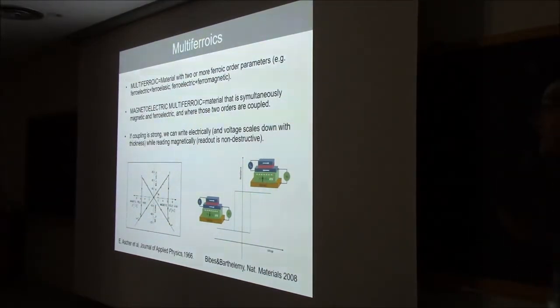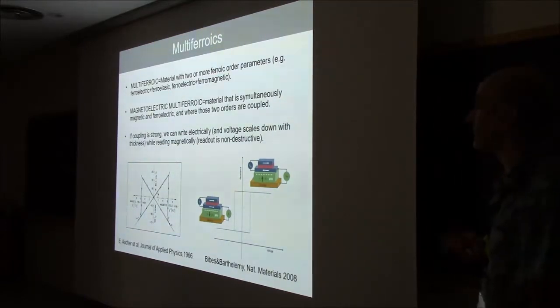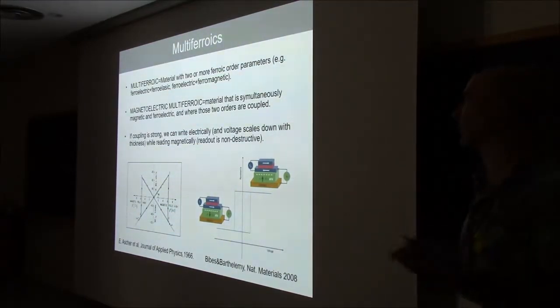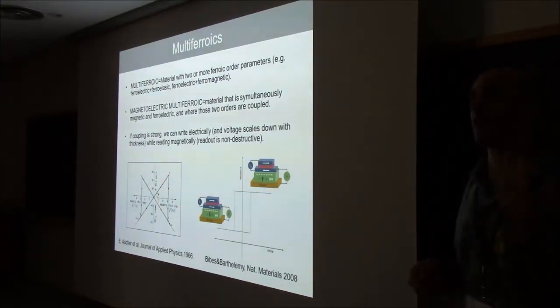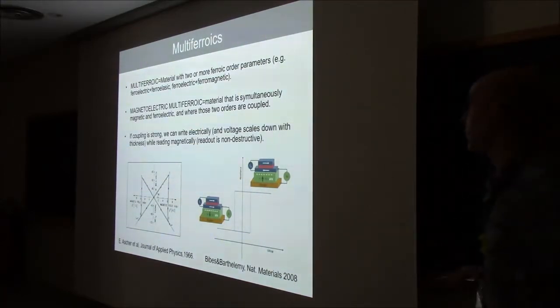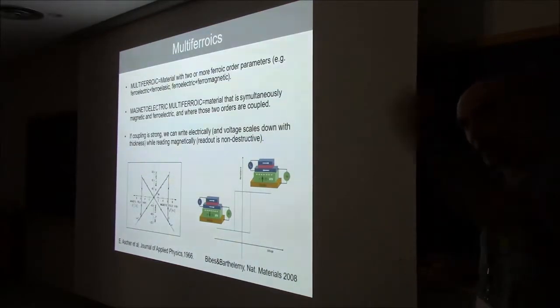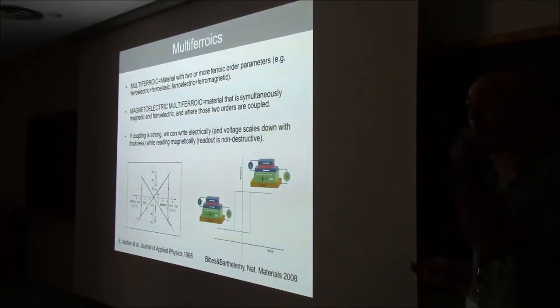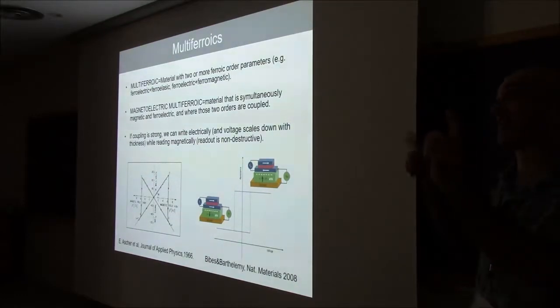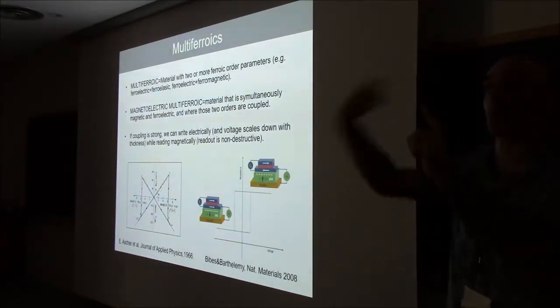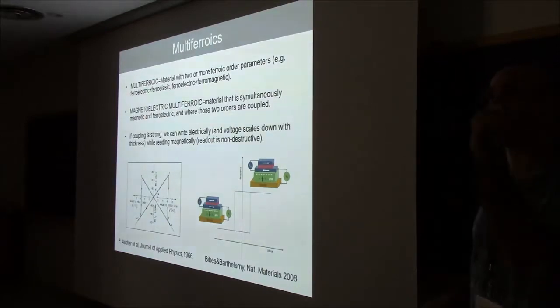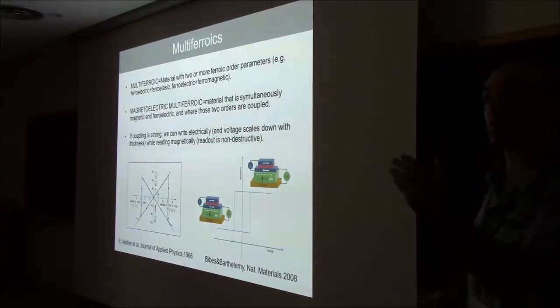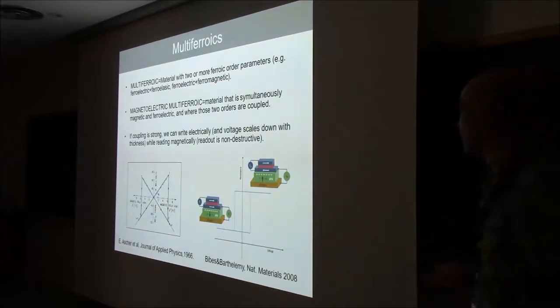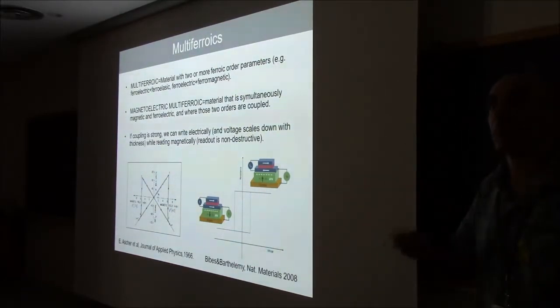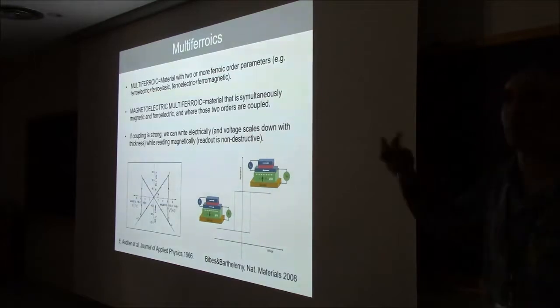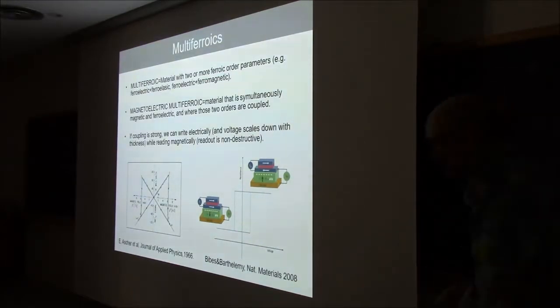material. The idea being that if you had something that was at the same time ferroelectric and ferromagnetic, and the 2 things were coupled, you could write your magnetic memory by applying a voltage. Okay, you apply a voltage, that changes the polarization, and if the magnetization is coupled to the polarization, the magnetization will also switch. So you can write it at a low energy cost because you're just applying a voltage, which in a thin film is small, remember? And then you can read it non-destructively using the usual machinery of spintronics.